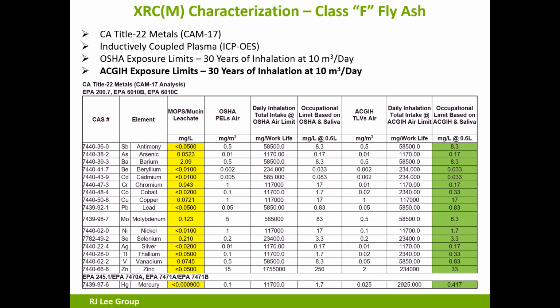So the way this works is we are envisioning that you would be inhaling, not respirable, but inhaling, dust from this product throughout the course of a day, and that during the day, plus 2 hours afterwards, you would be ingesting this metal through your nose, through your eyes, through your mouth, through your skin, plus 2 hours after work. So when we ran the numbers out for 0.6 liters of saliva per day ingested, that actually is a 10-hour workday, 5 days a week instead of 8, because we feel that for 2 hours after you get off work, you're probably still ingesting some of the dust. Most of it is blown back out of your nose, or it's spit out, or it's discharged from your skin by washing, etc. But there is a certain amount that we feel is ingested, and we used 0.6 liters of saliva per day to compare against the amount of air that you would breathe in per day of the metal-borne particulate.